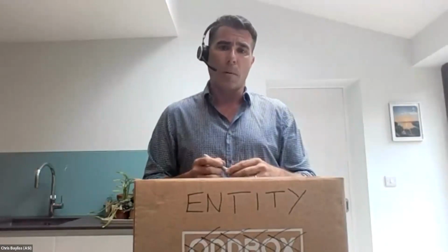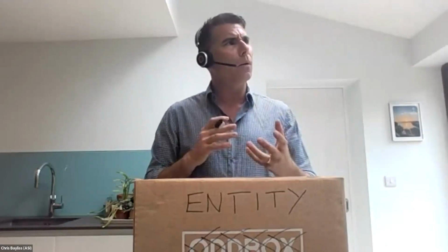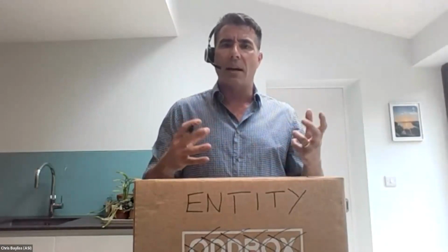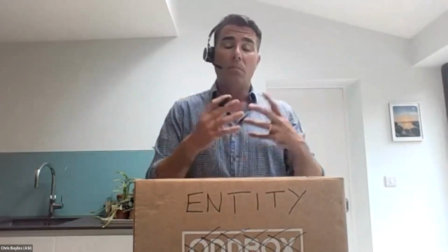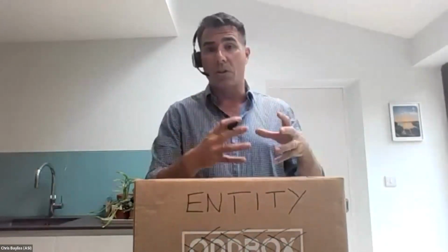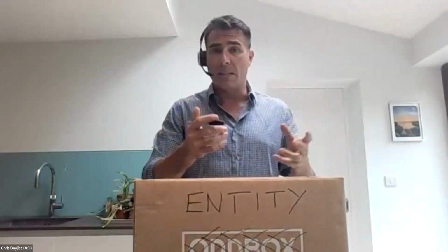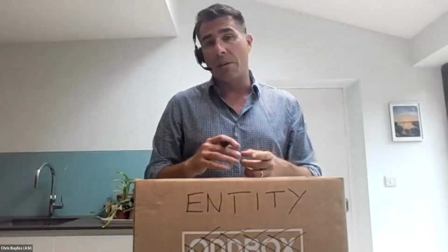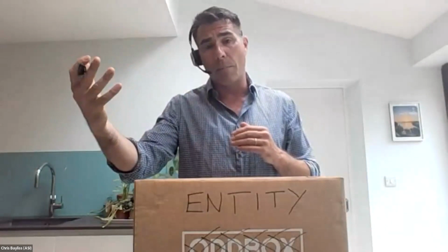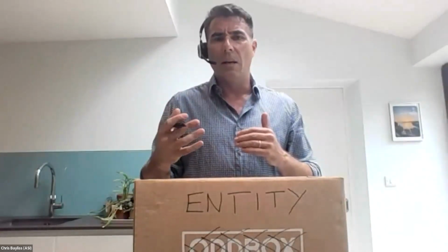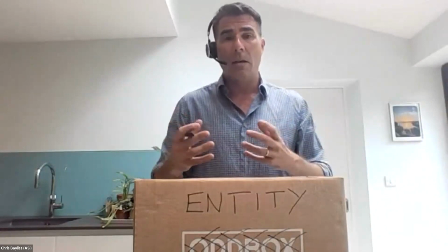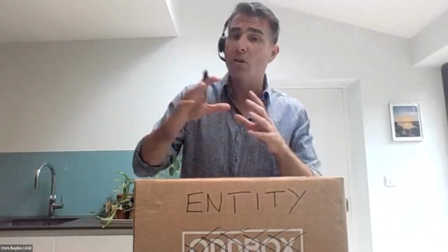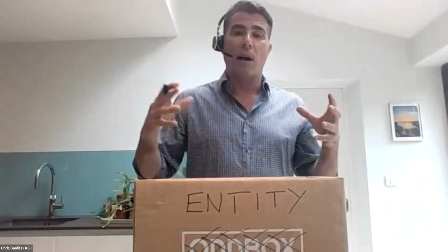It's dominated by post-consumer. Today, I think there's about 12 million tons of ASI aluminium, chain of custody certified aluminium, produced in the world at the cast house. Of that, around 500,000 tons is coming from post-consumer scrap, I would say predominantly can scrap, used beverage cans, and around 100,000 tons from pre-consumer scrap. So post-consumer scrap does dominate, but pre-consumer scrap is growing.